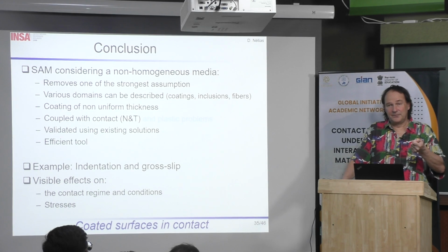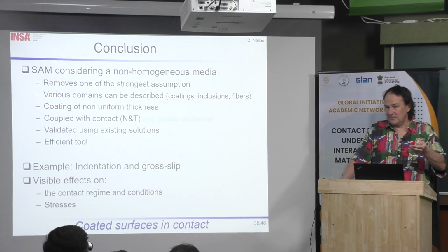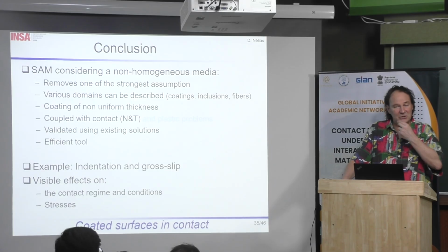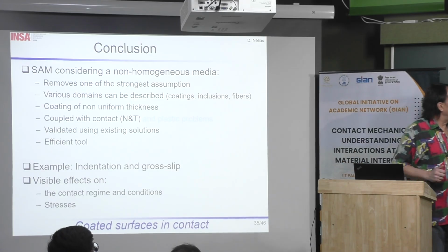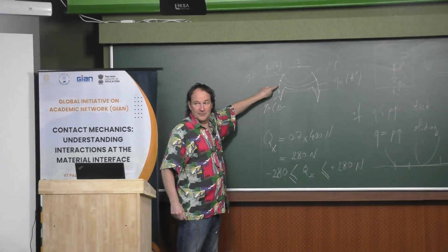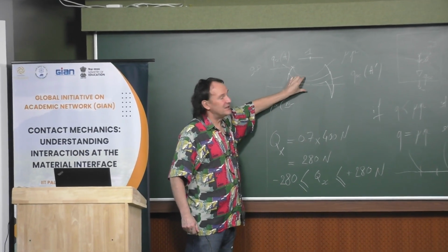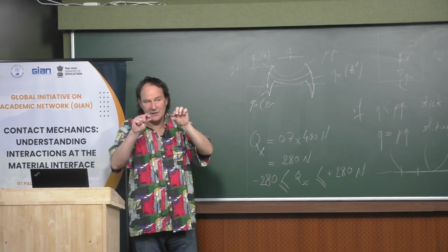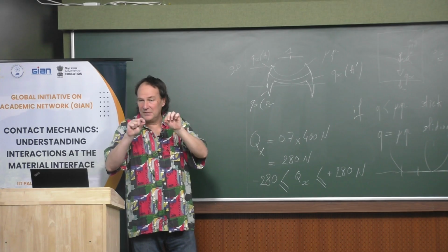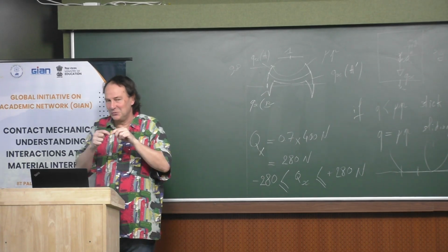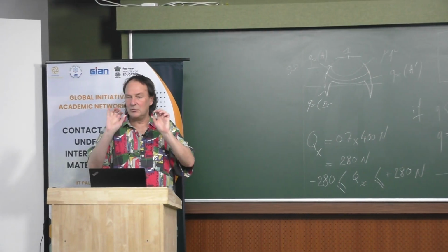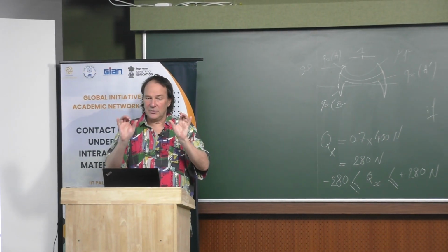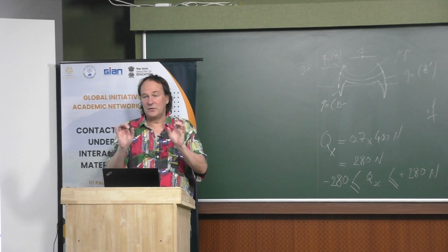First, you have oxide, especially if you have some humidity, some moisture, and oxygen, then you will have some oxidation. What you can observe is that oxidation occurs mostly in the sliding area, because the sticking area remains closed and there is usually no oxidation there, since no oxygen comes into the contact. Then oxidation is limited to the border.